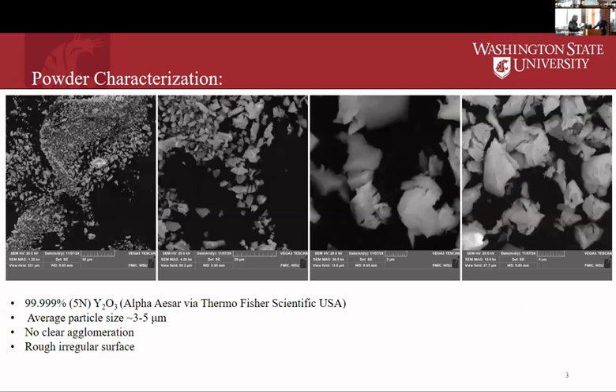So the first step we had to go through when producing transparent ceramics is powder characterization. The first thing we did was get some 99.999%, or 5N pure, yttrium oxide from Alpha Aesar, which is now Thermo Fisher Scientific. We did SEM imaging on it to see exactly what it looked like, and we found that the average particle size was approximately 3 to 5 micrometers.